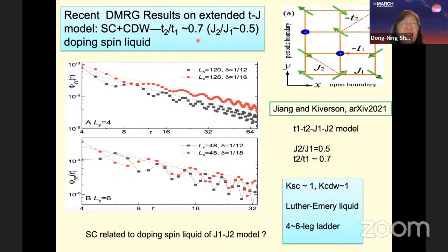Very interestingly, if we consider the large U Hubbard model, which is the TJ model, there are three different simulations around the same time. They all identify superconductivity. So those models, including second nearest neighbor hopping, put the half-filling phase into a doping spin liquid.